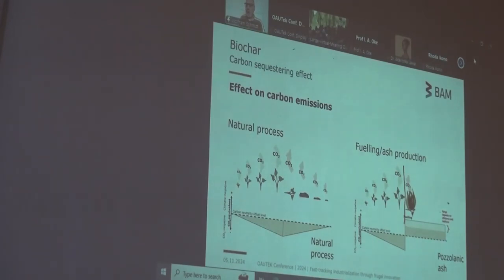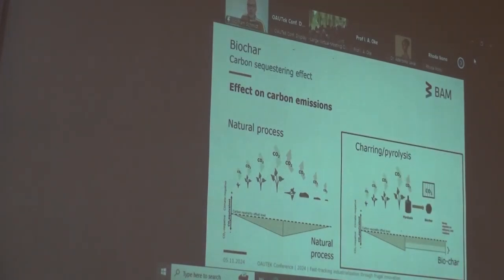But that would be climate burdening, not because of the CO2, but because of the methane and because of the nitrogen oxides that occur during the burning. The cleaner we do it, the more we can minimize this number here. So that would be a pozzolanic ash. But if instead of burning it, we could pyrolyze it, which means we convert it into a char, and this char captures the carbon, which means the final char product is CO2 negative.